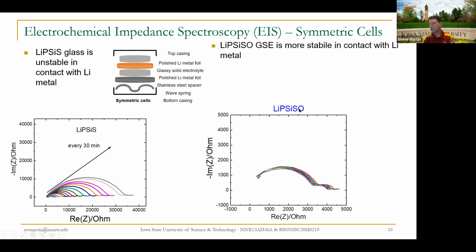When we add oxygen to the glass, we stabilize it dramatically. There's a little width here, but the impedance is 4,000, and we still get some interfacial contribution. It's hard to explain the whole complex impedance diagram, but this is due to the bulk of the material. A perfect response would be just one single line. It wouldn't change with time. Here it's changing dramatically, so we know it's reacting. Here it's changing a little bit, so the oxygen helps a lot.